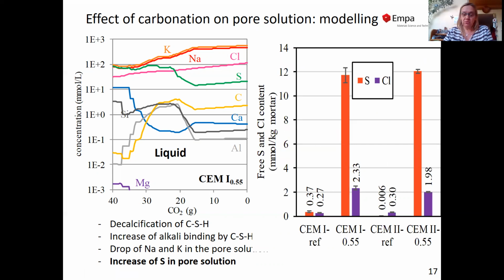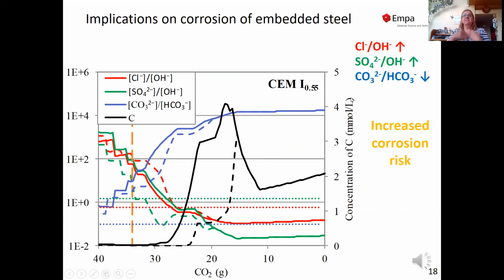We also saw in the cold water extraction an increase of sulfate concentration from the non-carbonated to the carbonated sample. And if we now ask ourselves what it means in terms of corrosion, we can have a look at the chloride to hydroxide ratios and the sulfate to hydroxide ratios, because they greatly affect the corrosion rate. And we can see that they increase, here in red and green, roughly by a factor of 100 from the uncarbonated to the carbonated samples. This gives us an indication that corrosion will be much more likely in the carbonated samples.